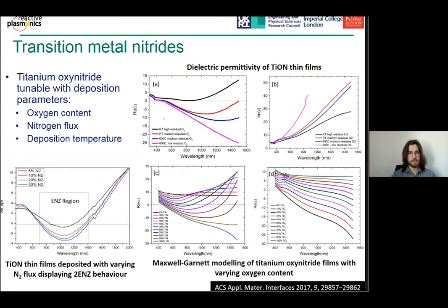And we see that titanium nitride films deposited at high temperature have typical metallic behavior and a Drude response in the real dielectric permittivity. But if we deposit at lower temperatures, we see that we get this double epsilon near zero behavior. And this is potentially interesting for optoelectronic and nonlinear applications. But we wanted to understand why we were seeing this behavior in the first place. And we found that it was due to oxygen incorporation within the thin films.